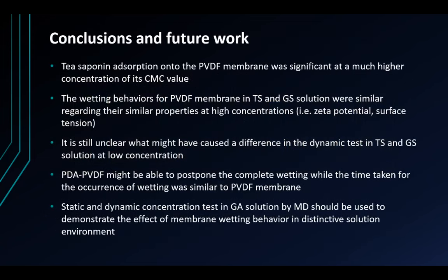We highlighted these findings from the work I introduced just now. Tea saponin adsorption onto the PVDF membrane was significant at much higher concentration than its CMC value. The wetting behaviors of the PVDF membrane in TS and GS solution were similar, regarding their similar properties at high concentrations. It is still unclear what might have caused a difference in the dynamic test in TS and GS solution at low concentration.